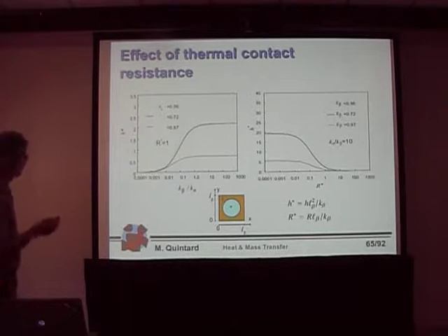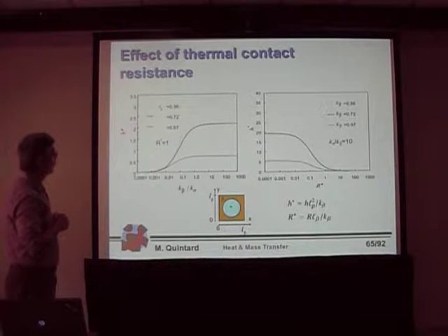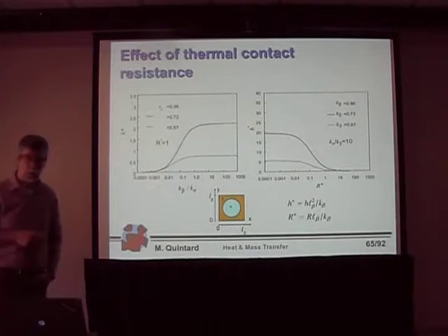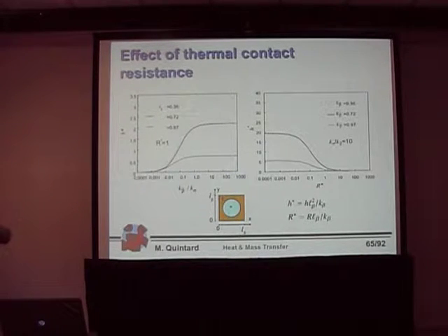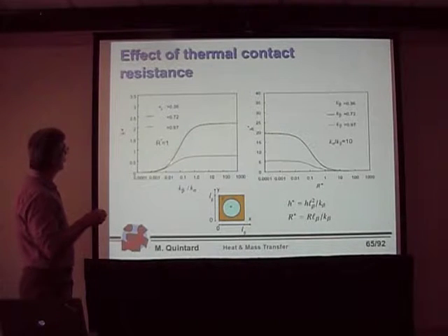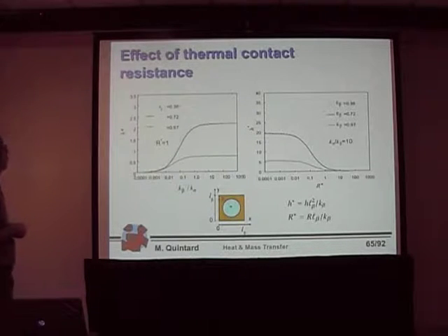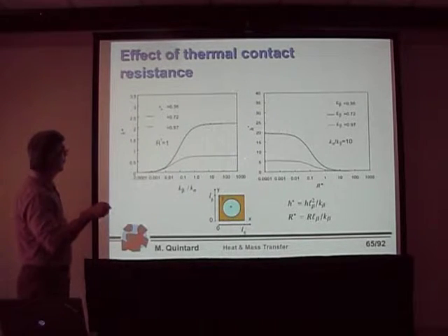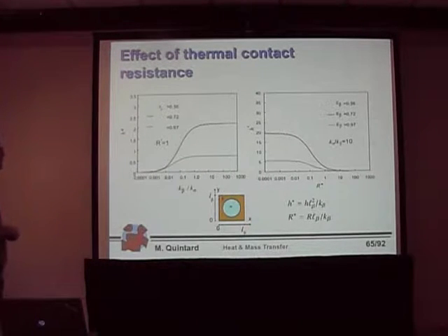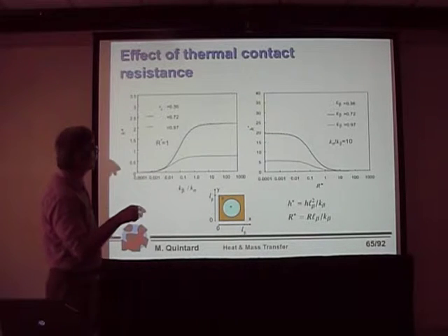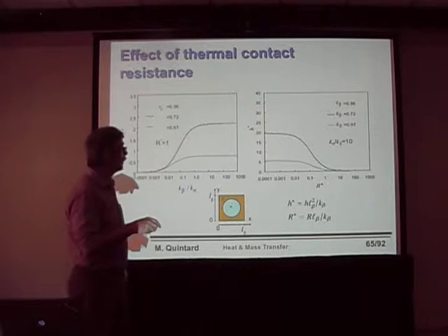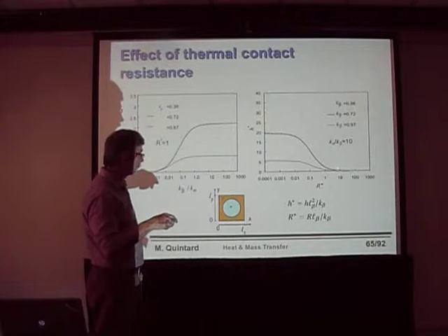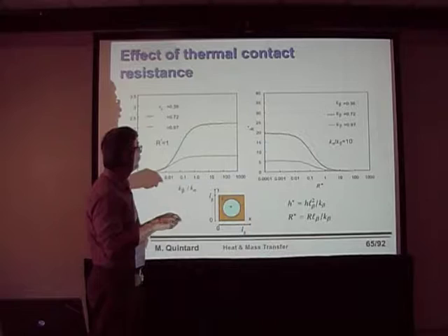To illustrate that, let us look at the heat exchange coefficient versus the ratio of the thermal conductivity of the beta phase and the sigma phase. And R is some dimensionless expression for the coefficient. So for a given heat resistance, I have the H that changes like that, something we already have seen previously. And now, if I take a single value, let's take, for instance, something near this plateau here, and I look at the impact of R. I have the following. So if R becomes very, very big, H tends to zero.